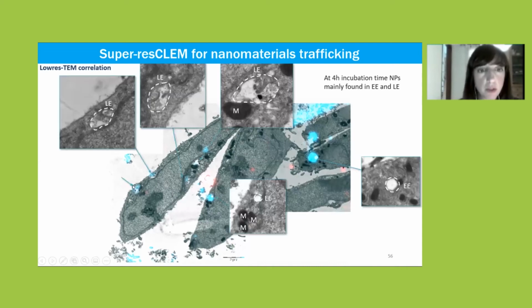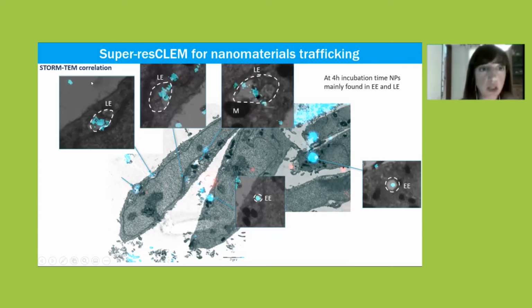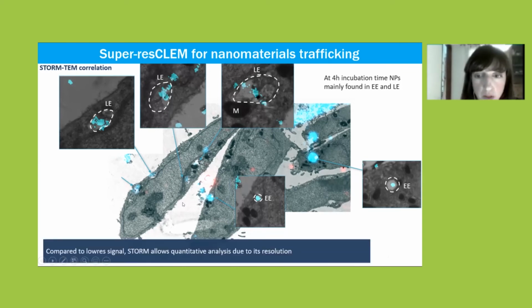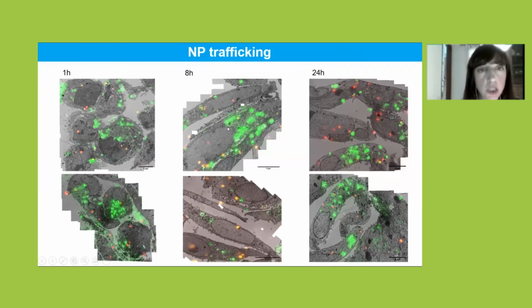So what we observe now is that the signal is located in different types of organelles, like late endosomes here, or early endosomes here or here. And when we overlap it with the super resolution image, with the STORM image, we can see how they nicely fit and they can be correlated very well. No? So compared with the low resolution signal, STORM is more quantitative and it fits better the resolution of electron microscopy. So we did this for different timings.